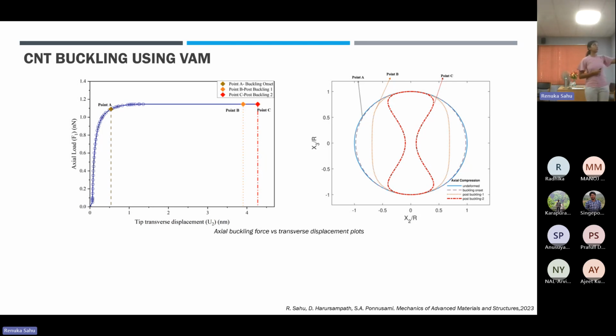Corresponding to all these points, point A, point B, and point C, we also have the cross-sectional shapes of the beam, which is usually not obtainable using normal beam theories. Here we can see that at buckling onset, there is a slight change from the circular cross-section. When you move to points B and C, which are post-buckling points, the CNT has an oval and a dumbbell kind of shape, showing highly nonlinear behavior.